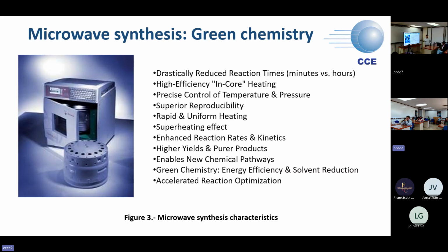At that moment, this kesterite was synthesized for very long times, maybe 24 hours, in some cases 72 hours. This means three days. So when I started to work with this material, I used microwave synthesis, and I achieved the same compound in only one hour, or even 15 minutes.